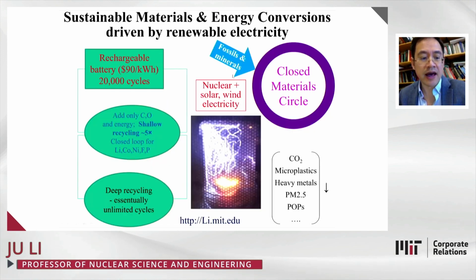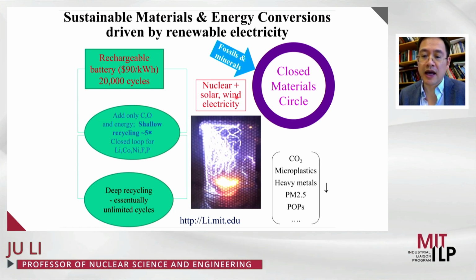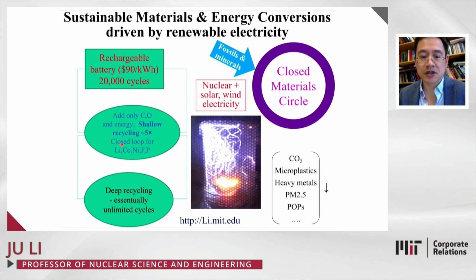So the long-term view is that we should have a fully closed material circle, which is driven by the nuclear baseload, combined with solar, wind, and renewables, and battery energy storage, which is powered by battery energy systems, which cost less than $100 per kilowatt hour at the system level, with the initial cycle life of 20,000 cycles. But then we can do light recycling, which form a closed loop for lithium, cobalt, nickel, and also we cannot release elements like fluorine or chlorine to the ecosystem. And then eventually we can do a deep recycling, which achieves essentially unlimited cycles.